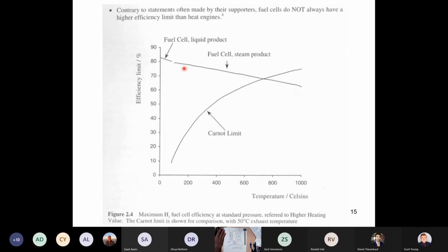So a fuel cell is much better than a heat engine over most reasonable temperatures until finally around 700 degrees C, you'd be better off just burning the hydrogen in a heat engine and extracting energy that way, as opposed to using the fuel cell. So this is kind of off topic to some degree, but you know, sometimes people say fuel cells always have a higher efficiency than heat engines, but at super high temperature they don't.